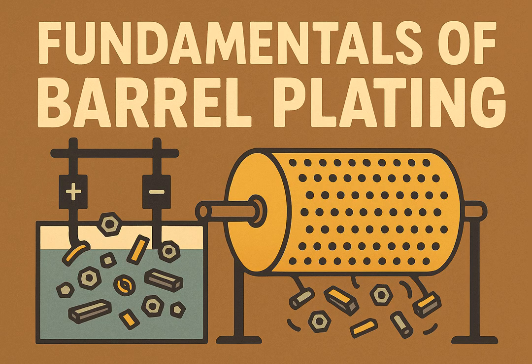That makes sense. What else is specific to barrels or new tanks? Another issue, relevant when setting up new equipment, is cloudiness in new nickel tanks. If a new tank lining, often rubber or plastic, hasn't been properly leached beforehand, the plating solution itself will start to leach substances out of the lining over time, causing a milky white haze in the bath. So the tank itself contaminates the solution. Can happen if it's not prepared right. Testing lining materials for compatibility with the plating chemistry beforehand is important to prevent this.